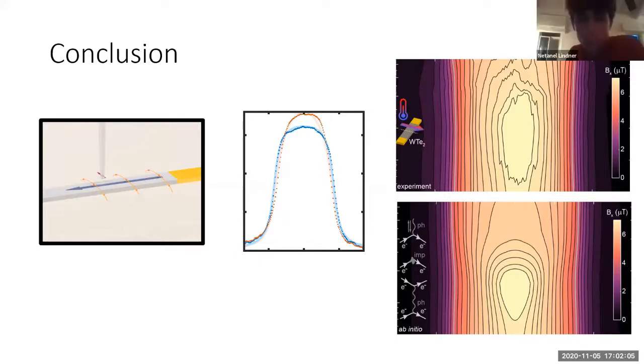I mean, it could be that it's just doped, doped Weyl semi-metal, doped enough. It seems like it's not very much doped, as I was saying before, because when we measure the Hall voltage, it's almost zero. And you also have very high magnetoresistance, which has to do with the same effect, the fact that you have almost the same number of electrons and holes. So we think it's very close to charge neutrality, almost compensating.